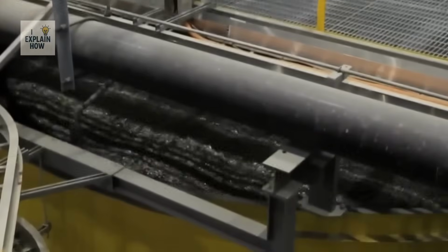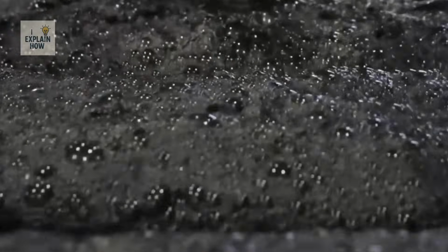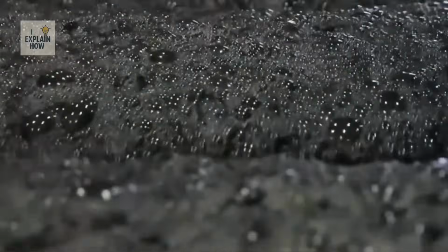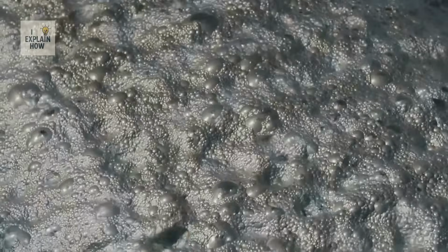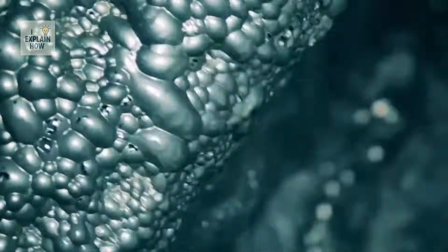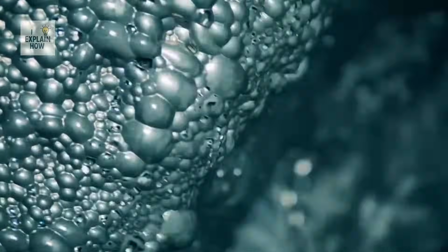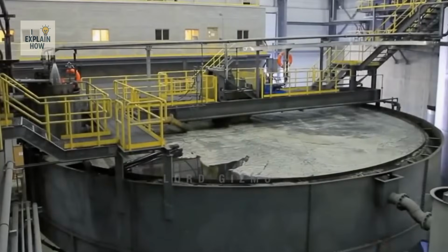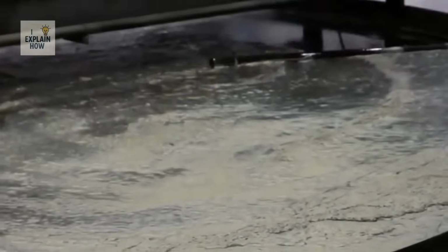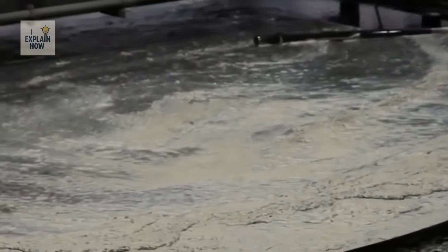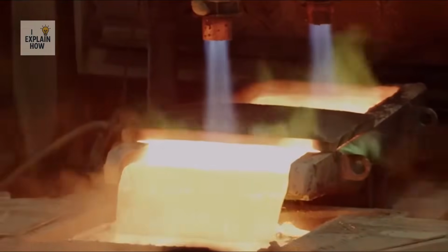Once the rock is ground into powder, chemicals are added to coat the copper particles, along with a frothing agent. This mineral slurry is then sent to flotation tanks, where air bubbles carry the copper particles to the surface. This copper-rich froth is collected and filtered to produce a concentrate with a purity of at least 30%. The next step takes place in the smelting plant.